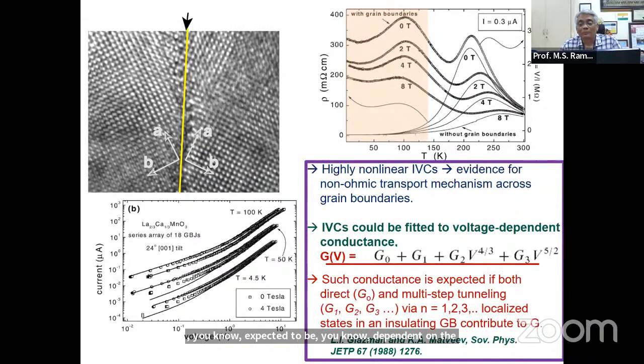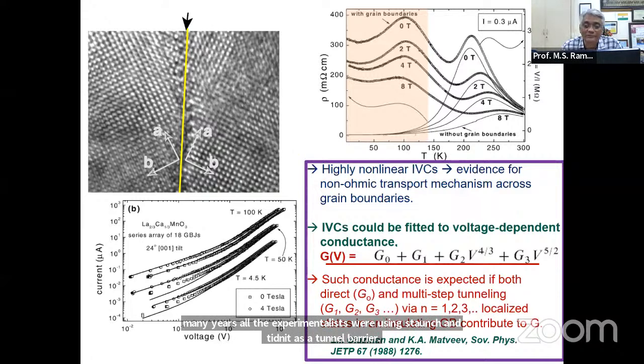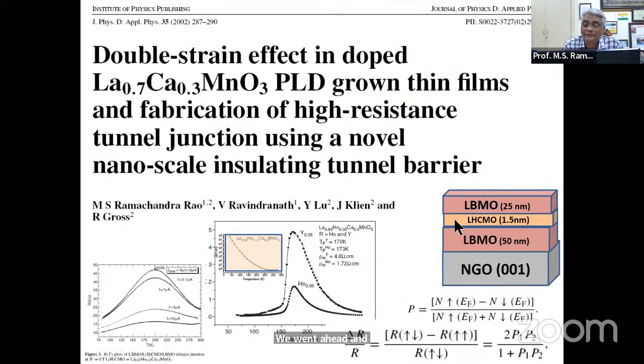So this prompted us, since for some reason for many years all the experimentalists were using strontium titanate as a tunnel barrier, to go ahead and replace it with an insulating manganite itself. That means if you take LBMO, which is typically a ferromagnetic metal, and you overdope it with a transition metal element, at a certain concentration it becomes an insulator. So we use that insulator.